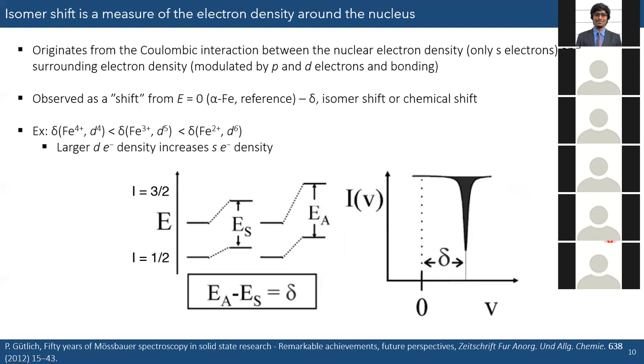To start off, the isomer shift is the most simple one to think about. This is a measure of the electron density around the nucleus. As I talked about before, in the source it's going from an excited I equals 3/2 state, relaxing down to the ground I equals 1/2 state, and in that process it emits a gamma ray. This gamma ray is then absorbed in the absorber material and excited from 1/2 up to 3/2, which is why we attain the absorption peak itself.